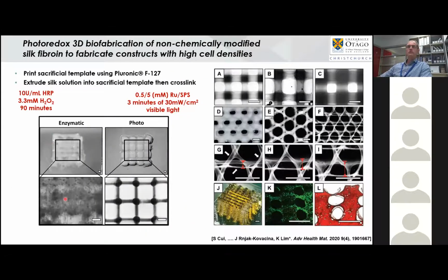That was compared to generally enzymatic cross-linking, and for the interest of time, I won't go into a whole lot of detail and just refer you to the paper. But of course, with silk hydrogels, the main big advantage is that we can rapidly cross-link these within minutes, whereas the enzymatic cross-linking often takes very, very long periods of time. So we can rapidly do this, which is very important for cellular incorporation.